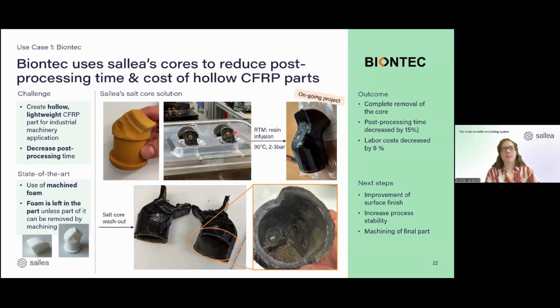Here you see two examples. So we did two cores at the same time. Then the mold was closed and the resin was infused. The process was done at 90 degrees Celsius, and 2 to 3 bars were used. And then after a few hours, the part could be removed from the mold. And here you see the resulting part. Of course, the resin is all around, so it's hard to see the core, but it's mainly here inside, and here is the second part of the core.